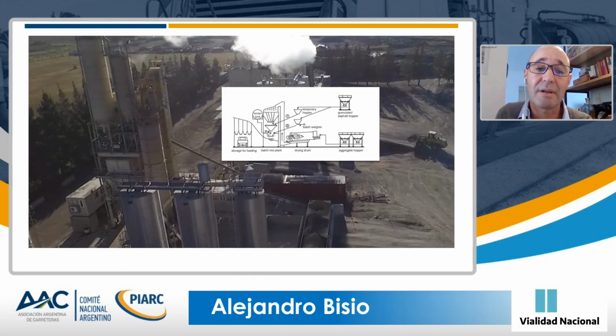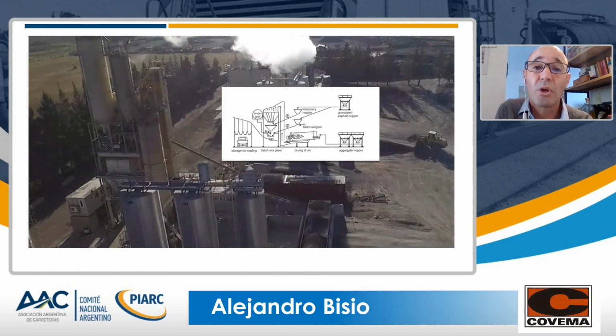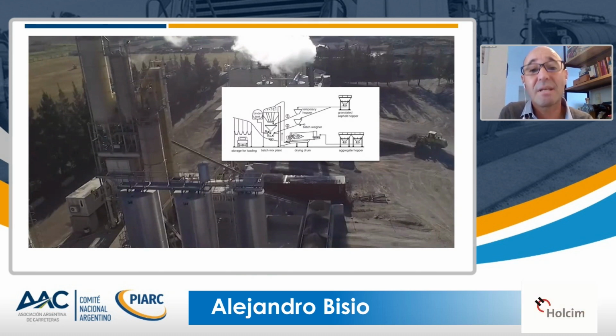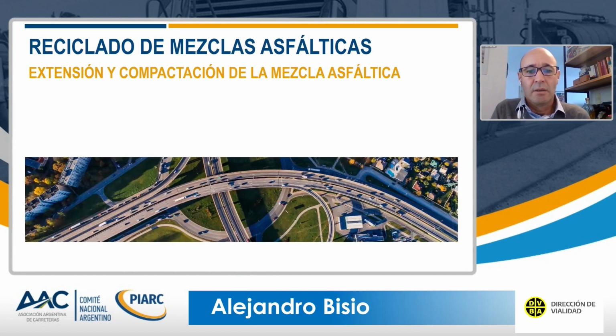So if the objective was to keep temperature constant, a difference between the two processes has to do with the temperature of virgin aggregates. In the case of batch plants, the temperature of virgin aggregates was higher in order to compensate that 20% wrap coming at room temperature, at ambient temperature. But we didn't find any significant difference in the rheologic property of the components of the asphalt mixture when they were produced by the two different methods.